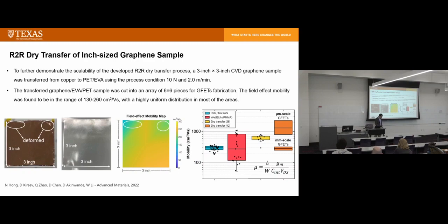The largest sample we have been able to demonstrate is 3 inch by 3 inch. It's already huge compared to other transfer samples. It's also in a roll-to-roll process. So we take this 3 inch by 3 inch sample and mount it on our rotary roll machine. We peeled it, and this is a transferred 3 inch by 3 inch graphene on PET/EVA.